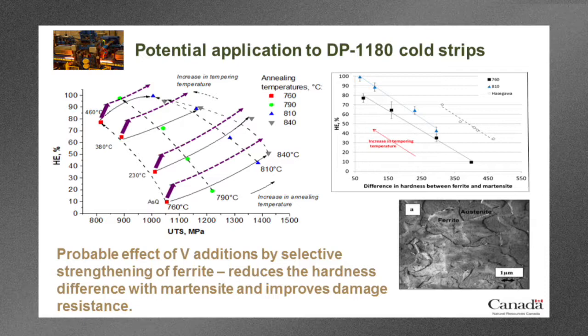So if we could do that, then that would naturally shift this graph up along this axis here. The combined effect of those two different mechanical behaviors would be to shift this graph some angle, which could be 45 degrees, we don't know, up towards this top right-hand corner of the graph, which is exactly where we want to be: high hole expansion and high ultimate tensile strength.